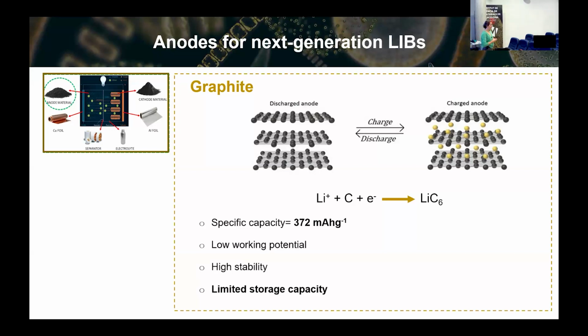But the need of increasing the energy density of the batteries is making graphite look not that great, because we will need to have much more capacity than what we currently have. And the amount of lithium ions that can be intercalated in graphite cannot be higher than the theoretical numbers. So we cannot put more lithium in there. So we are actually limited in graphite. We cannot enhance the capacity more.